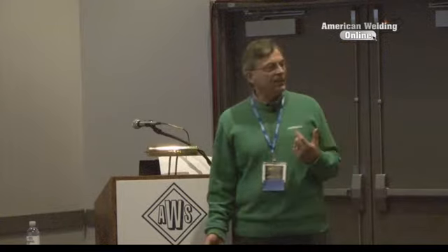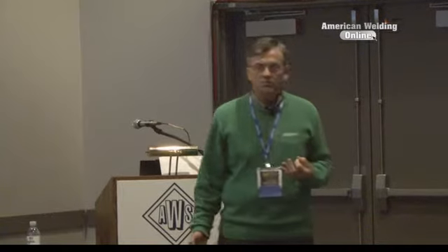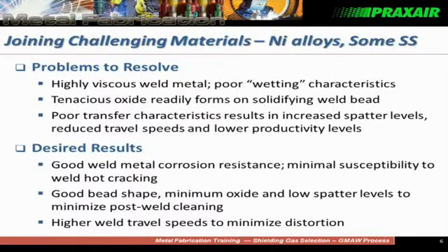So the example that I'm going to use is one, if any of you have welded high nickel alloys, sometimes stainless steels, but typically high nickel alloys are very challenging materials to weld. One of the reasons is the weld pool is very viscous. It's not fluid. It doesn't want to flow well. So you tend to get weld beads that are not very well wet out. Travel speeds are slow because, again, the material doesn't want to flow.